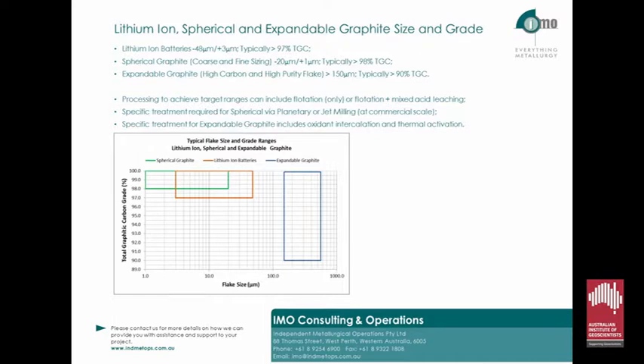It is interesting that a lot of company classification is based around the final concentrate flake distribution. However, the most hyped growth in the industry for graphite, the lithium-ion battery market, requires fine graphite, albeit spheroidized in either a jet or planetary mill. IMO's research has led us to conclude that jet milling is really the only option to commercially produce spherical graphite, and during that process, approximately 40 to 50% reports to spherical graphite. The discussions I've had with my clients have indicated that it's the lack of flake being supplied from China, balanced with flake demand, that is the real reason for the higher jumbo flake prices compared to finer flake prices.